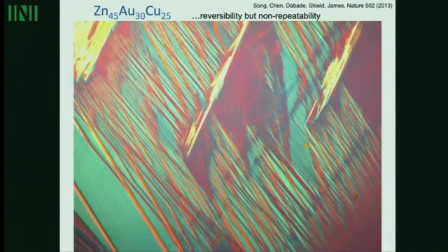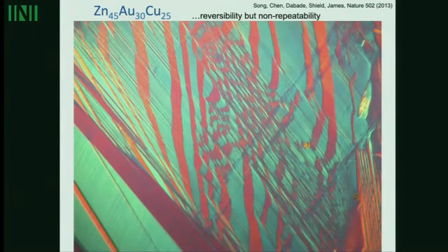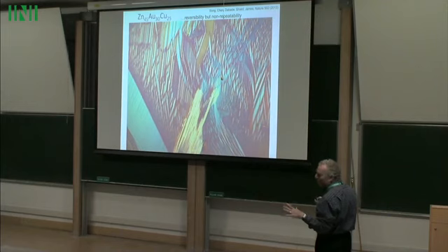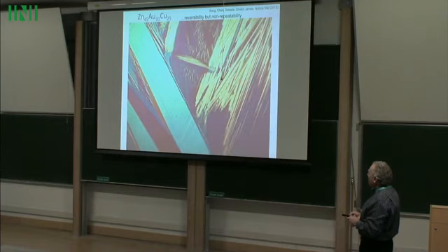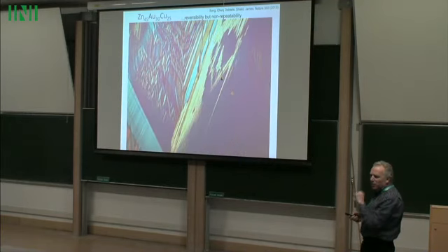It's quite unusual. Another thing about this, that Francisco Della Porta may speak about later, is that when the interface passes by, right behind the interface there's very little relaxation. The microstructure is set already behind the interface. But that's a very strong restriction on microstructure, because every point has to be compatible with the austenite at some previous moment.